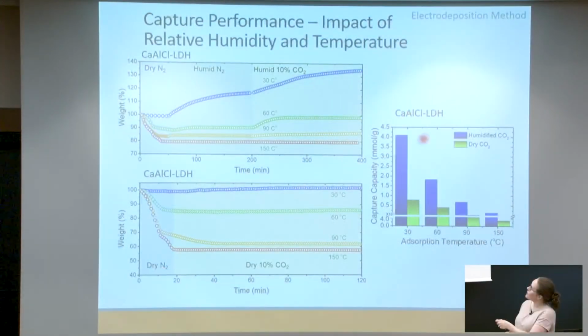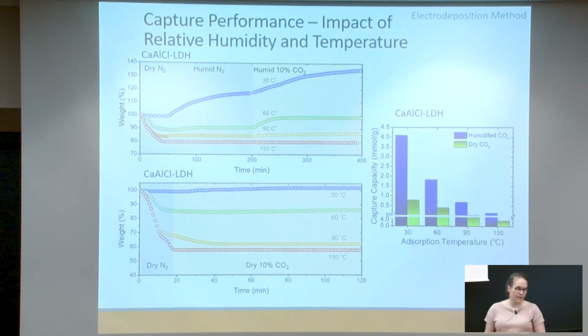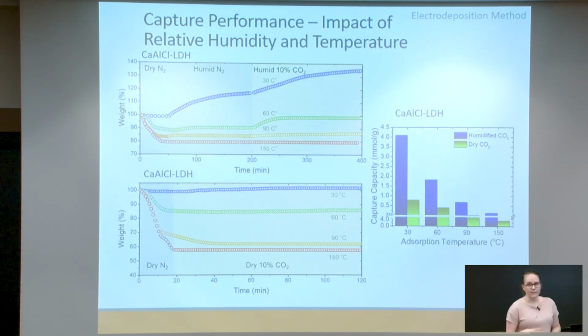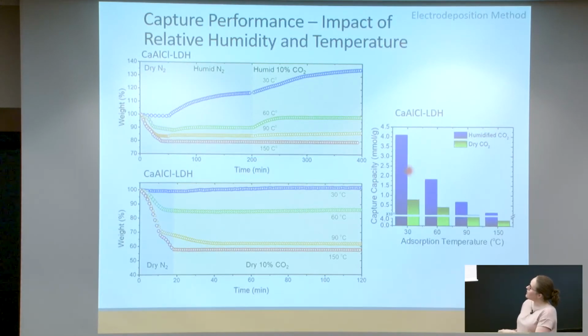So we've also looked at the impact of relative humidity and temperature on the capture capacity of this layered double hydroxide. Specifically, now we're looking at the anion exchanged one. What we see here is that if you have humidified CO2, about 60 to 70% relative humidity, we've got a capture capacity of about 4 millimoles of CO2 per gram of sorbent. Whereas if you have dry CO2, then the capacity is significantly reduced. Once again, we're really interested in this intermediate range of relative humidity to see if we can get more sorption of CO2, but a lower energy requirement for regeneration.